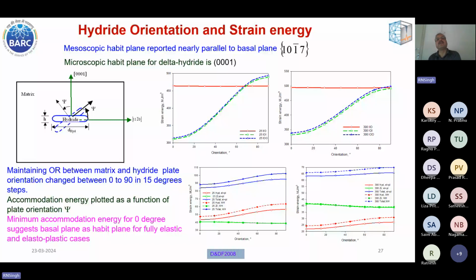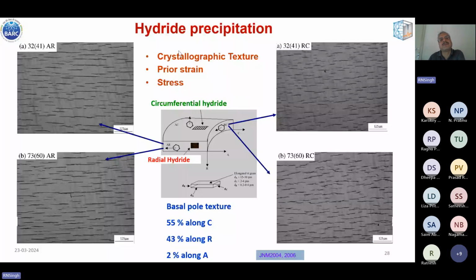Hydride precipitation is governed by crystallographic texture, prior strain and stress. Suppose this is a section of a tube, in which the basal pole texture is like this. It is about 55% along the circumferential direction, 43% along the radial direction, and hardly any basal poles along the axial direction. So what this means is that crystallographically, there are two orientations possible. One is this orientation, called circumferential hydrides. And another orientation is called radial hydride.